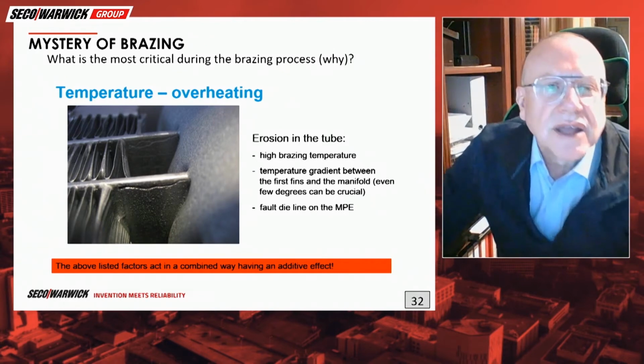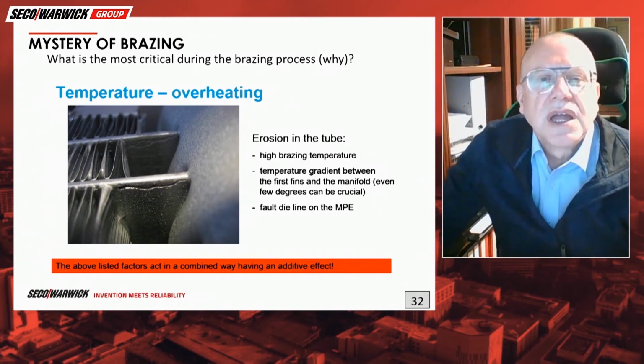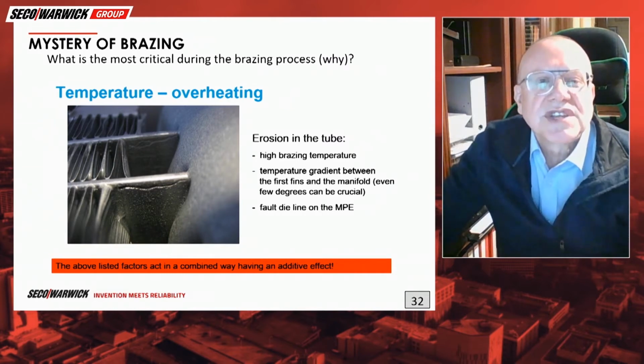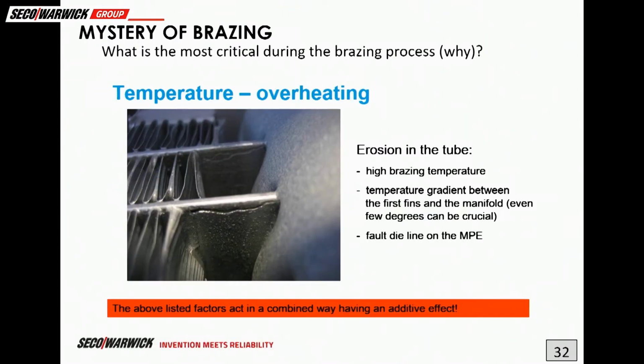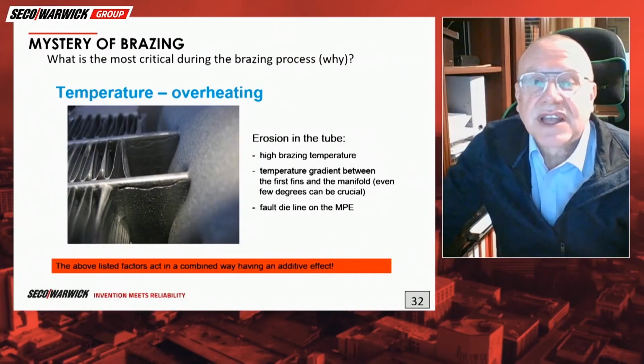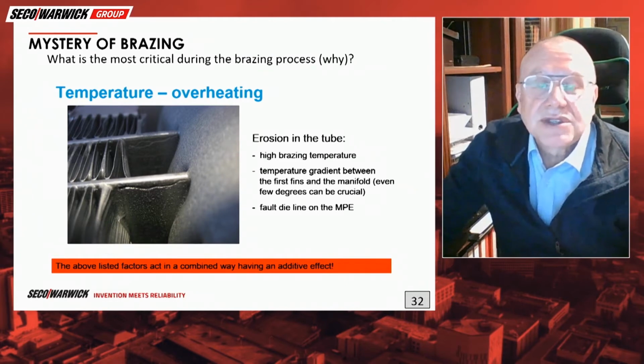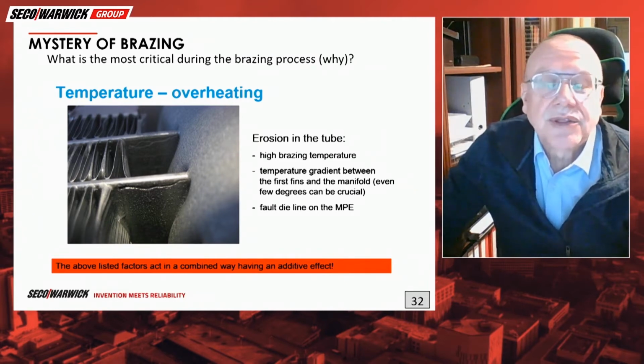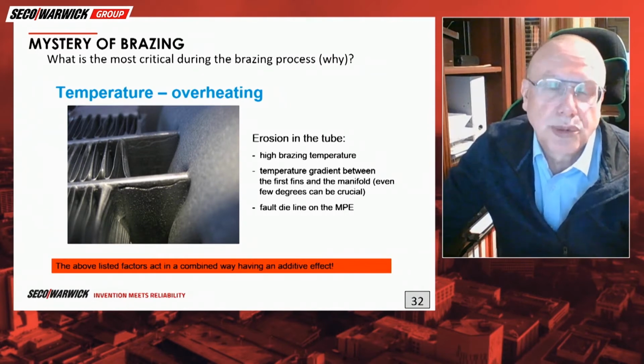This is a car radiator, and you can see that there is a line on the tube caused by filler alloy flowing towards the fin. That flowing filler alloy dissolved the material of the tube and created a hole in the tube, a total reject. Such things can be caused by high temperature, also by temperature gradient between the first fin and the manifold, but also it could be the so-called fault die line on a multi-port extrusion tube.